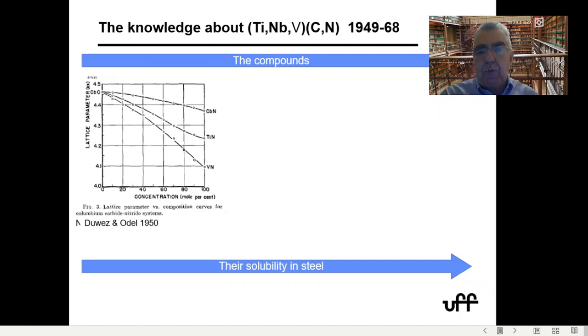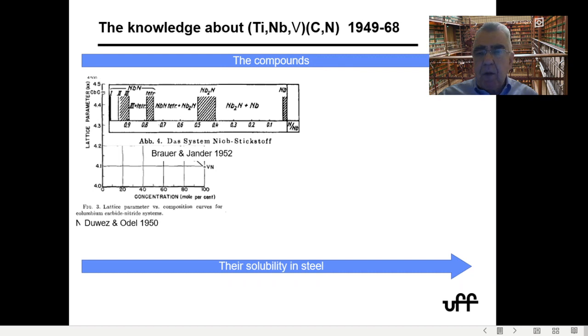So we see that these cubic carbides were fairly miscible and in a wide range of compositions. Also interesting was that back in the 50s too, it was observed that the stoichiometry of the NbN, for instance, was not exactly 1-to-1, but it was somewhere here. This was a little bit lean in nitrogen. So this was an important observation too.